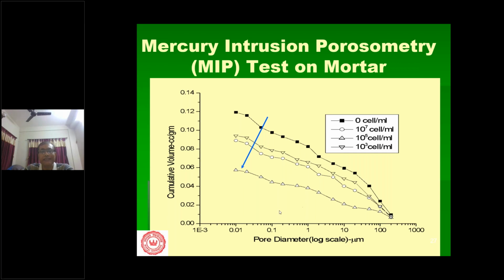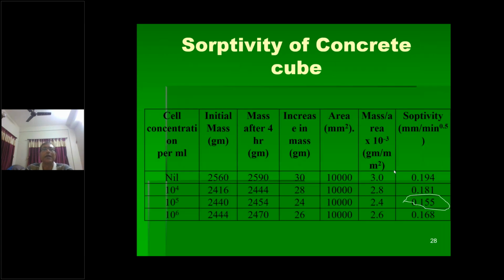In this graph, the x-axis is the pore diameter and the y-axis is the cumulative volume. As we see, at 10 to the power 5 cells, that is the lowest curve, at any particular pore diameter the cumulative volume has been reduced, and the pore diameter is also reduced. So it indicates there are some changes made in this concrete matrix, or the cement matrix.